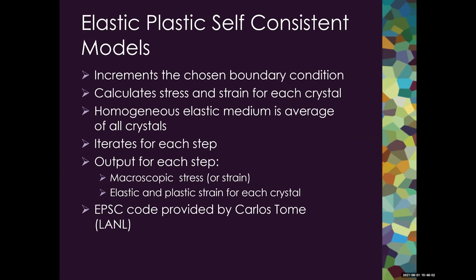So the model takes all this information and increments the boundary condition chosen, and the code runs through and calculates the stress and strain for each crystal. So the model continues to iterate until a consistent solution is found. And then the model output for the EPSC model is the macroscopic stress and the elastic and plastic strain for each crystal. And the code that we're using was provided by Carlos Tomé at Los Alamos.